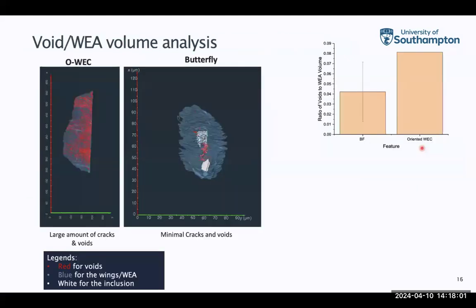So we did some analysis of the voids or cracks versus the whitening area volume using the 3D images we obtained for one of the oriented white-etching cracks and one of the butterflies. We found that the oriented white-etching crack appears to have a large amount of cracks. The red is for the voids, blue is the white area, and white is for the inclusions. You can see this oriented white-etching crack has a lot of voids, compared with the butterfly, which only has a very small amount of voids. We quantified them and found that the ratio between the voids and the whitening area for the butterfly is much less than for the oriented white-etching cracks.